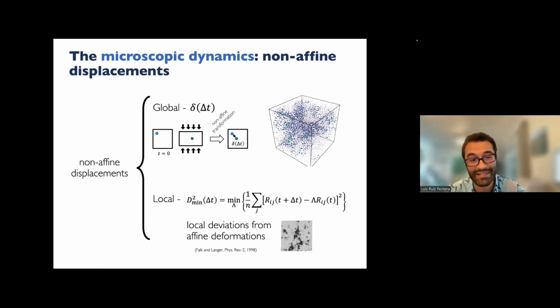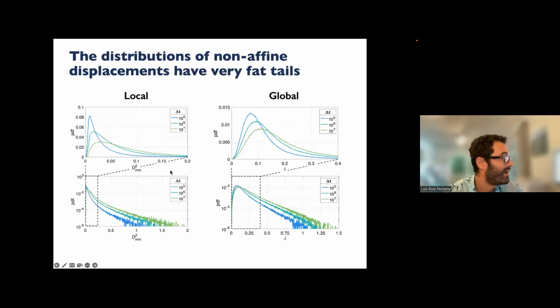So we have these two metrics. How do they look? Let's take a look at the statistics. In these plots, on the left you have local non-affine displacement, on the right, global non-affine displacement. The four plots are the probability distribution of the displacements. On the top, you have them in the linear scale, and in the bottom, in the semi-log scale. Again, these displacements are measured with respect to the initial configuration.